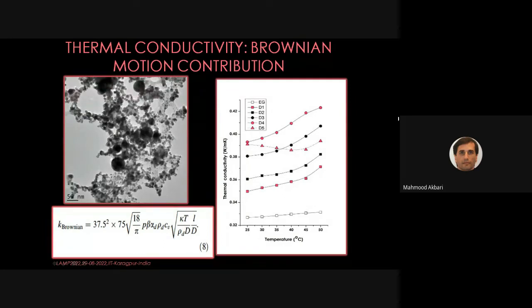And indeed, by playing on the equations, it is possible to find that the Brownian motion is proportional to the square root of the temperature, and inversely proportional to the size of the nanoparticles, and therefore the relatively rapid increase above 40 degrees Celsius. That is due to the Brownian motion, and it shows clearly that at a lower concentration the Brownian motion can play a major role.